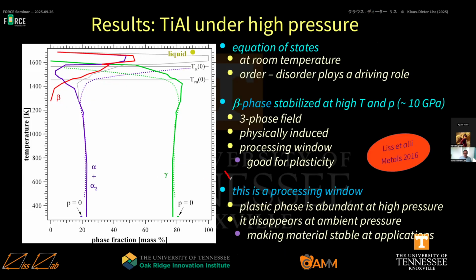So I'm talking about this. This is a processing window where the plastic phase is abundant at high pressure and it disappears at ambient pressure, making the material stable at applications at intermediate temperatures, which are around 1000 Kelvin. If we had the beta phase already at ambient pressure, then we would expect more creep in the system. So that resumes a little bit what I said.